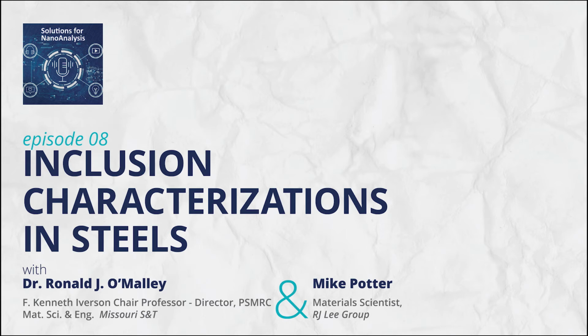That understanding also helps us understand the evolution of the inclusion morphology, because these emulsion inclusions will be converted by the killing process, but won't completely consume the oxygen in the oxide form. And then they form very complex shapes after that by growing branch structures off of this heterogeneous nucleation site. And all of this, I'm sure, sounds very technical, but what it really says is that the shape and morphology of the inclusion is very much dictated by that early stage practice in the EAF, which is something a lot of people have not talked a lot about in the steelmaking process.